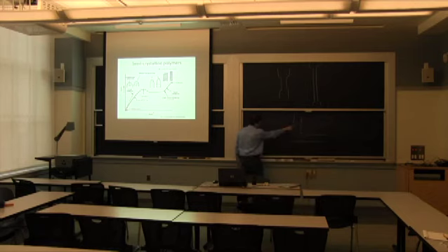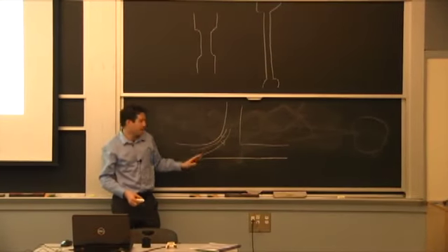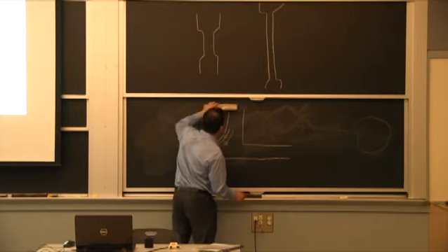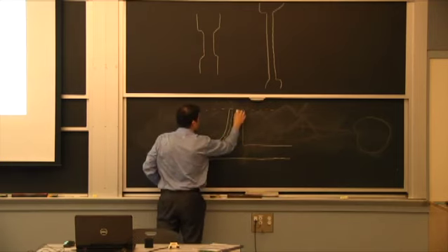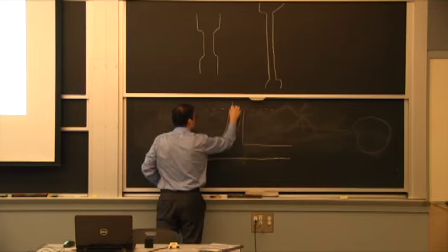If your goal is to mold a product, in the case of the blue part here, say I have my wall going this way, and then I have some extra material here. If this is going to be a high stress region, what I would rather have is the flow going through it, because that creates a little bit of a boundary layer. It helps the characteristics of my skin. I just want to have as much flow out there as I can. But if this is the center line of the part, you get the opposite effect, because when you start completely filling this in, you're going this way, you get it this way, and then you do the same the other way.